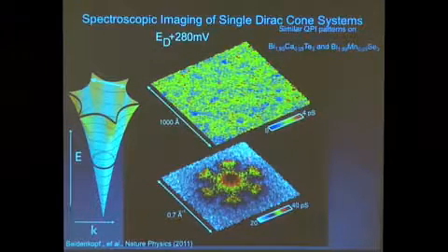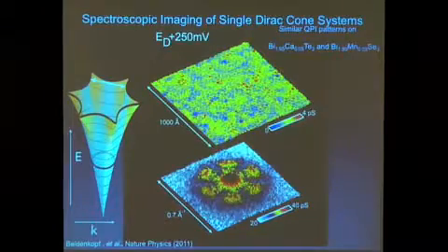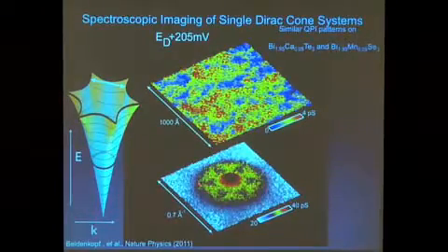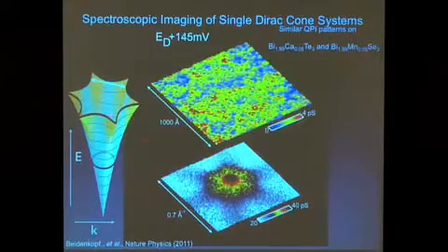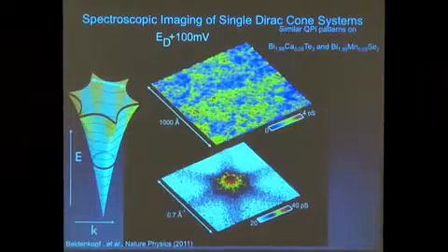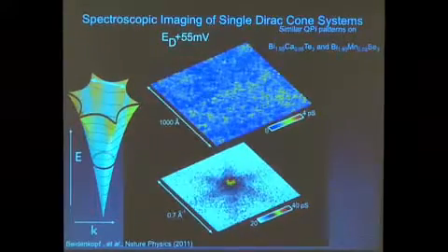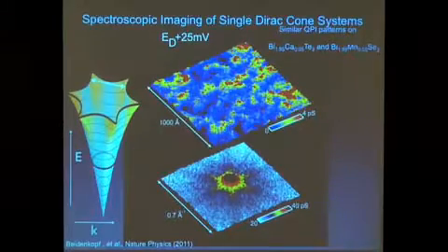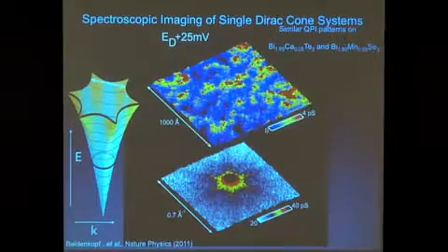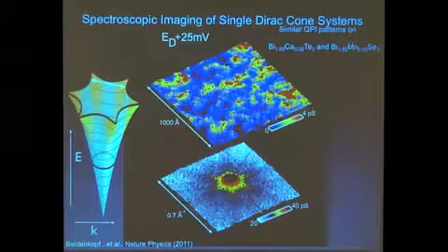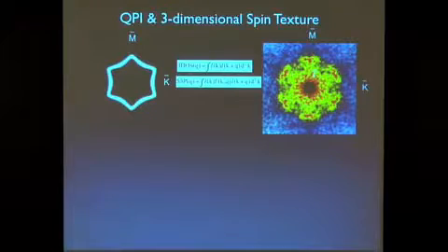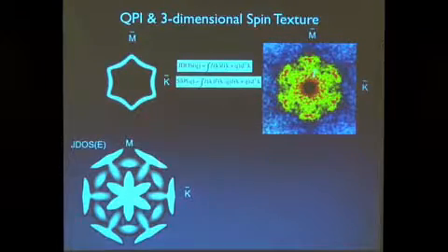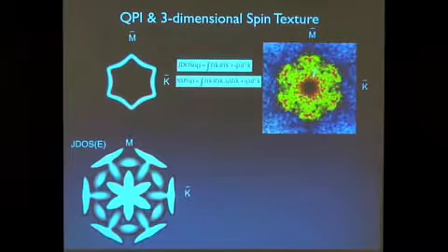And when you do the interference experiment on this sample, you also see a great deal of real space structure, which in momentum space gives you very beautiful data, which is related to this Fermi surface. What's satisfying about this is that you can actually image electrons basically having this linear energy momentum dependence all the way down to the Dirac point on the surface of this compound using the STM. Now here, it turns out the same idea basically works. You have a Fermi surface that looks like this. And you can ask, how can I understand the STM data? Again, you can forget about the fact that you have any kind of forbidden scattering, and just think about all the allowed ways that you can scatter.